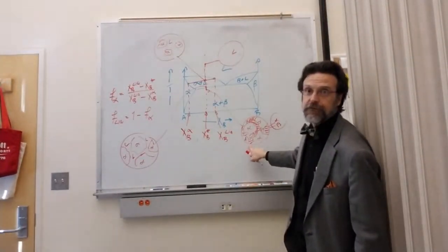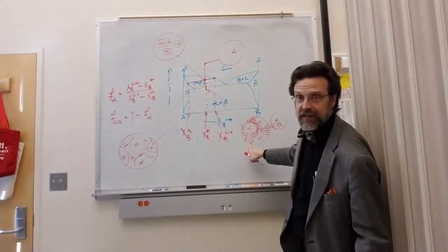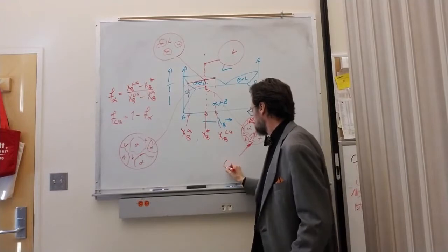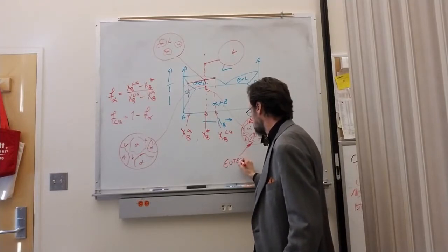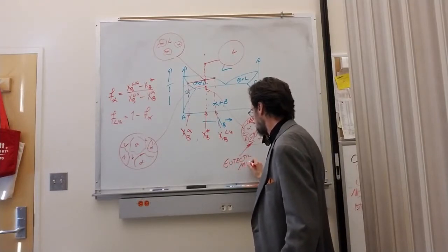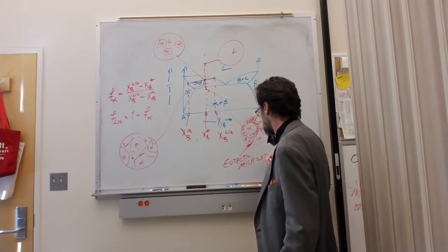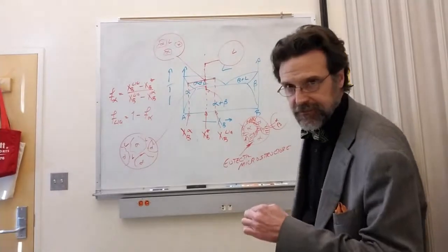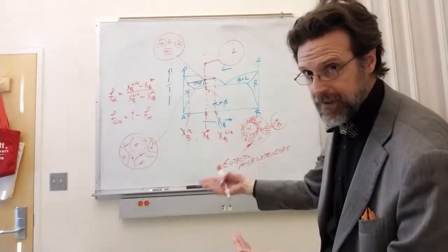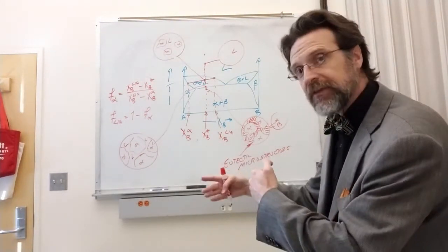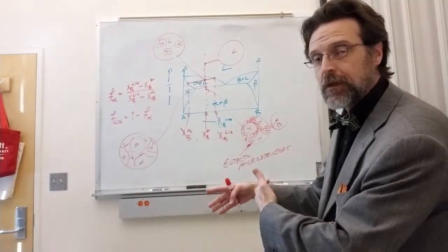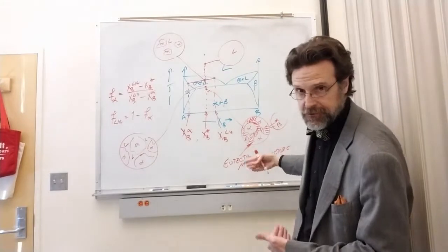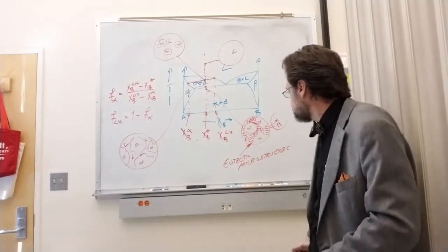This type of stacking, this lathe structure, is called a eutectic microstructure. It's not a eutectic phase. The only phases are alpha and beta. But the way that we arrange those gives us the microstructure, and this type of sequence we call a eutectic microstructure.